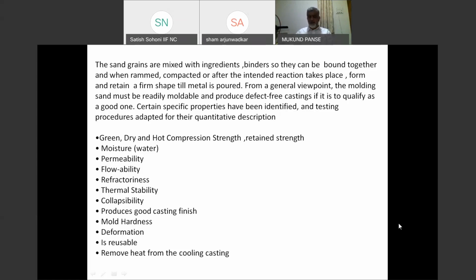Green strength is the strength of a mixture in the green stage. This is applicable mainly to green sand. Dry strength is after the mold has been dried. Hot compression strength is the hot strength of a mixture. This is required to be high so that the sand doesn't get eroded when the metal is flowing through it and it retains its shape. Retained strength is the strength of a sand after the metal has been poured and when it is cooling. The retained strength should be as low as possible so that the casting cools and the contraction takes place without any hindrance and you don't get hot tears and cracks.